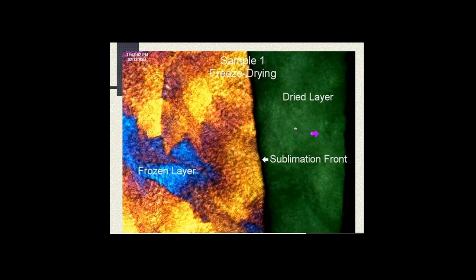There's a magenta filter in here. So if we see a magenta color coming through, we know we're starting to collapse. This is the sublimation front, where it's a razor-thin line where we're actually converting the ice directly from a solid to a gas. Well, then once we collect this image, we're going to start warming this sample up because I want to force it into a state of collapse because it shows me that temperature where we physically start to lose structure.